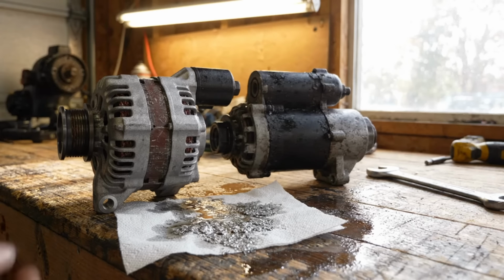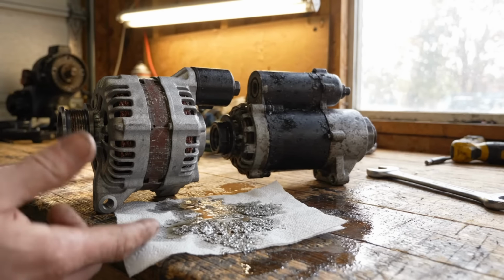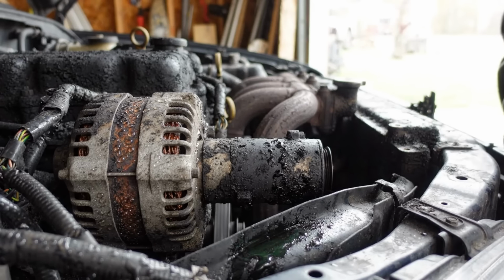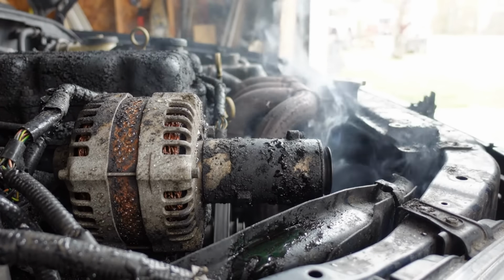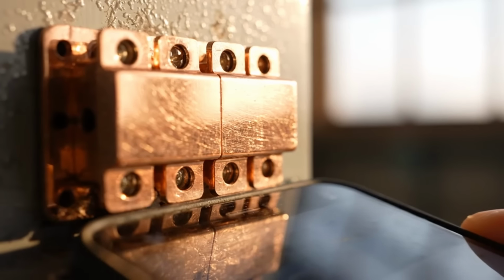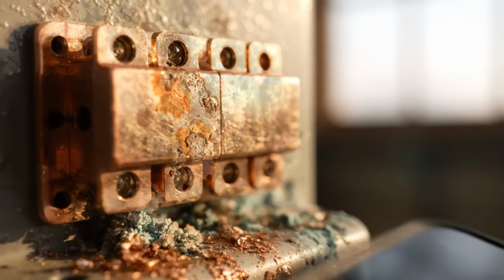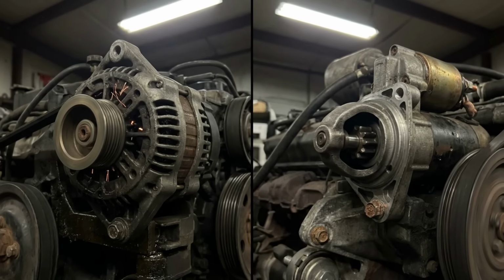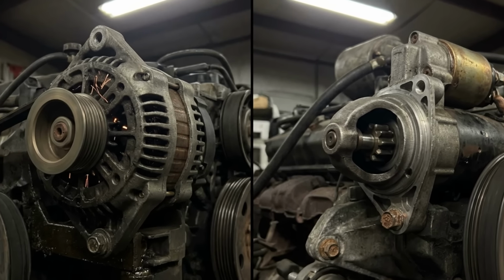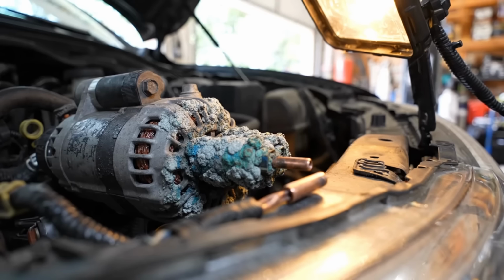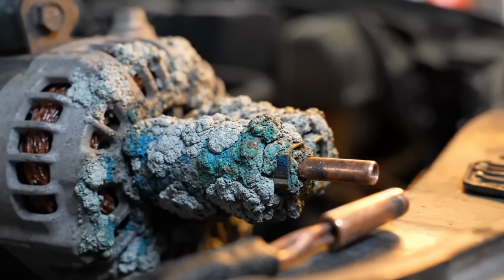Trick number 7. Clean corrosion from alternator and starter terminals. The alternator and starter are electrical components that sit in the engine bay where they're exposed to heat, moisture, and salt spray. Over time, the terminals corrode. When the terminals corrode, the electrical connection weakens. The alternator can't charge the battery properly. The starter can't draw full current. You might notice that the battery won't hold a charge even though it's new. Or the starter is sluggish even though the battery is good. The problem is often corrosion on the alternator or starter terminals.